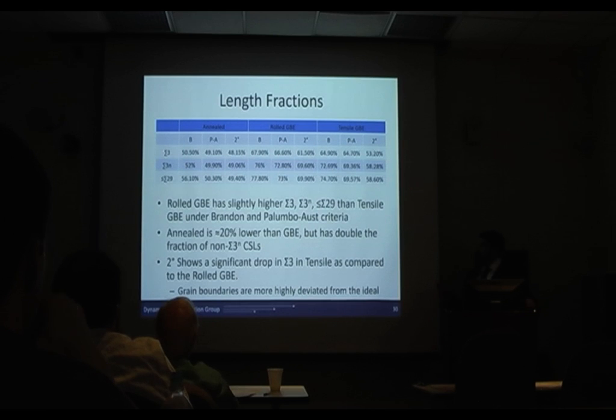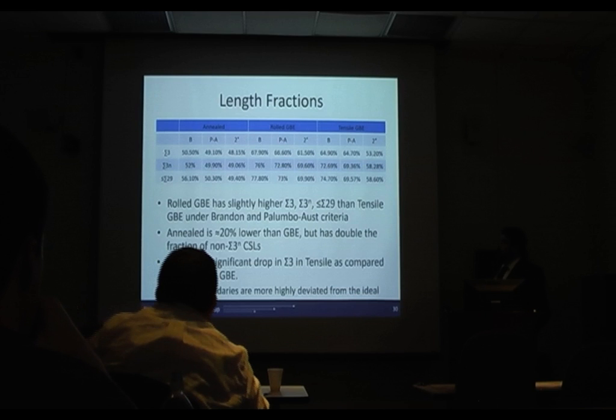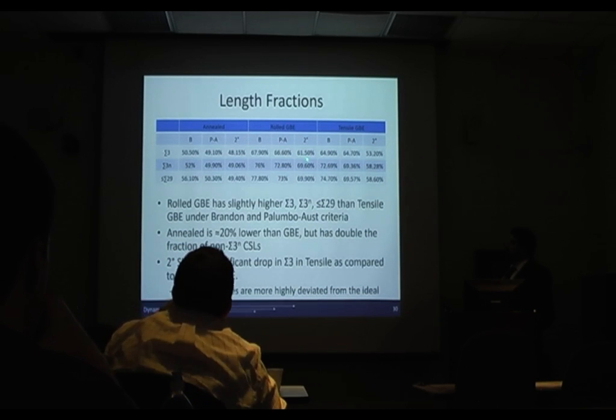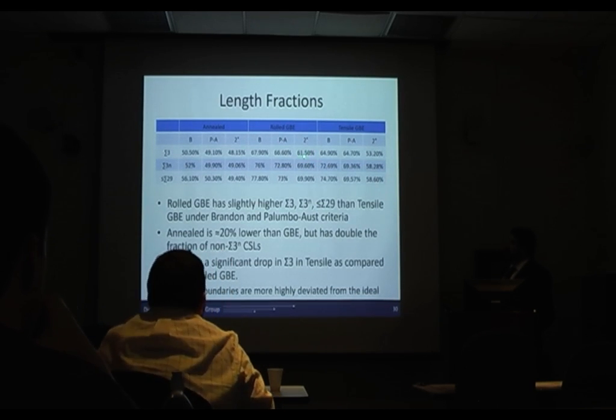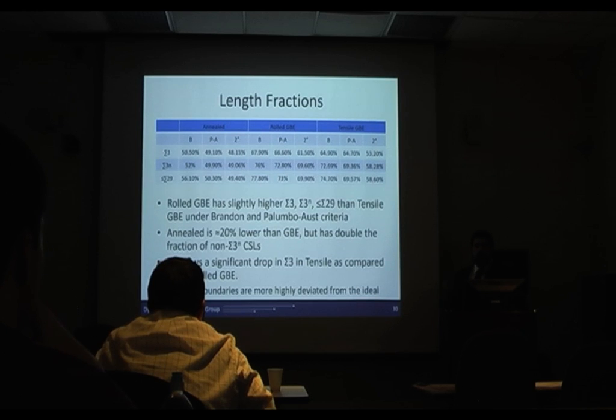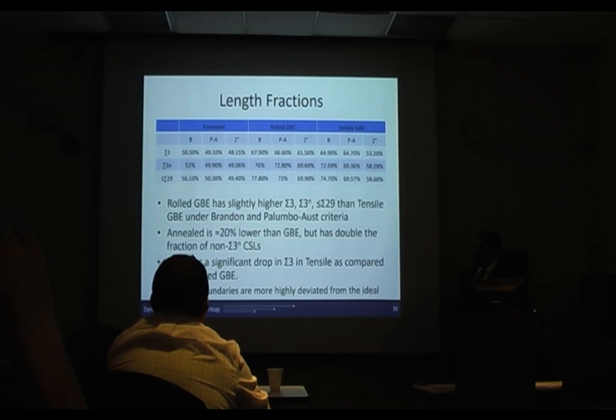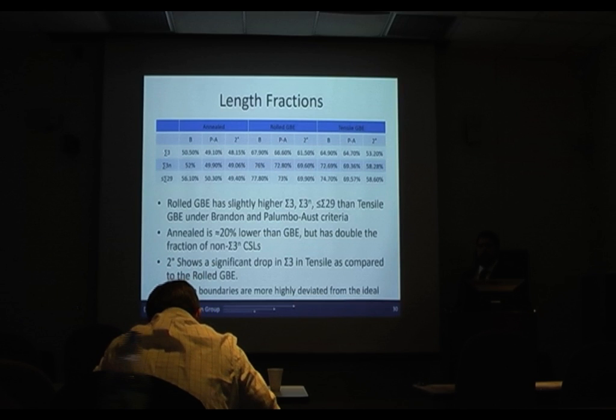But the really big difference that kind of surprised me with this was the length fraction of sigma 3s under the 2-degree criterion, 61% for the rolled GBE, and it's down to 53% for the tensile GBE. And what this denotes is that in the tensile GBE, the sigma 3s are actually more highly deviated from the ideal. They're still within the Brandon criterion, but there's a significant percentage of them that are beyond 2 degrees.